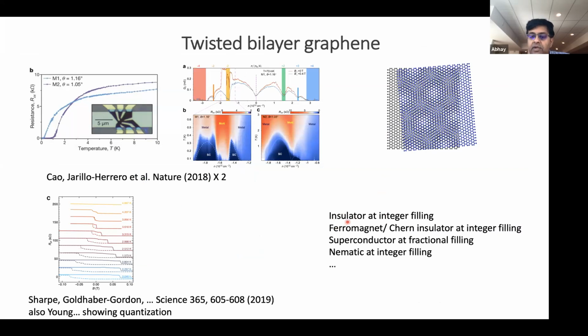And so it's been observed that at integer fillings of this Moiré lattice, you see insulating behavior that should not occur in the single particle picture. For certain special integer fillings, ferromagnetism has also been observed with non-trivial Chern number associated with it. Superconductors have been seen when you dope away from integer fillings. We've seen some evidence for nematicity at integer filling in twisted bilayer graphene. And I put the 3 dots here just to say that who knows what else is there in this system. There might be even other interesting things.